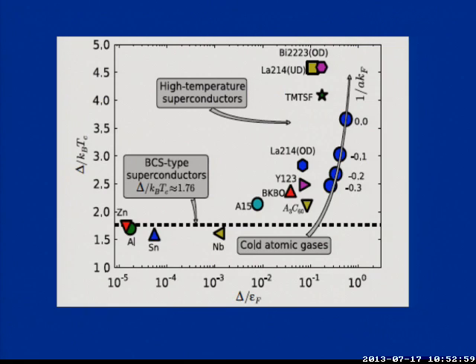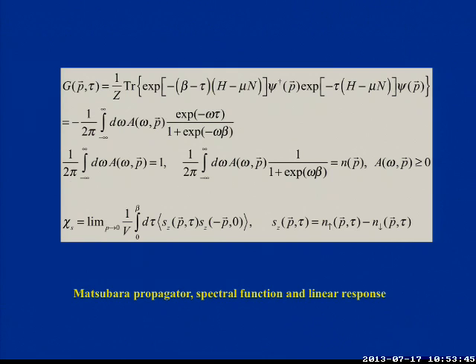And this, I think, is pretty solid. Okay. Now, about the systems. If you make a plot of the gap over the critical temperature, gap over the Fermi energy, and put all the fermionic superfluids there, known, BCS-like superfluids lie on this line. High temperature superconductors, they're here. Cold gases are here. Okay, so you see this is a very interesting system. Extremely large gaps, large critical temperatures, and this exceeds on the other side. What do we know about this? There is the so-called pseudogap. So let me talk a little bit about that, because there are at least 2 or 3 topics I want to talk about.